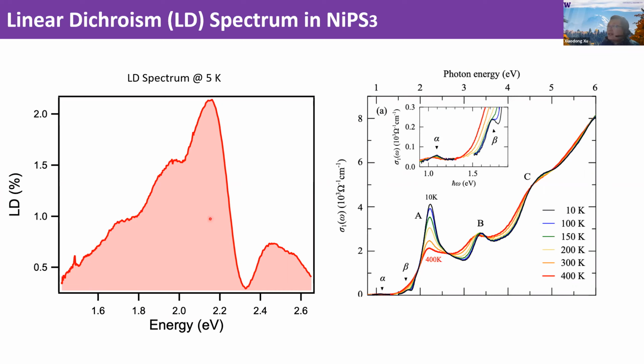Okay. So looking at this plot, I can already identify this charge transfer exciton A, which gives rise to this peak in the linear dichroism spectra. And we can also identify a bump we call beta in the literature. So this little bump beta also appears as this little shoulder here. But in the regular optical reflectivity and optical conductivity measurements, you will see just a smooth background and nothing happening.